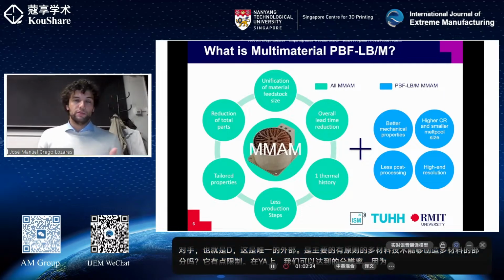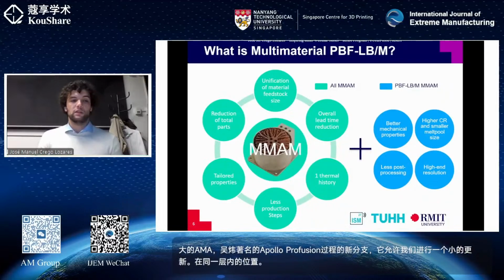So what is multi-material PBF? Multi-material PBF is just a small branch so far, it could get bigger. A new branch of the well-renowned powder bed fusion process with a small update. It allows us the deposition within the same layer. This allows us, again, as I said, to have transitions of materials not only in the building direction, but also within the same layer.